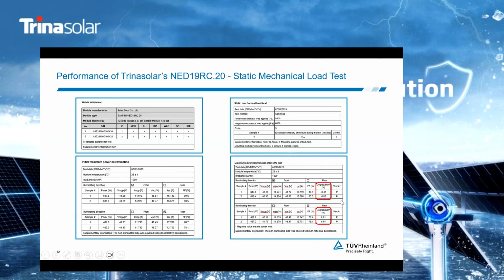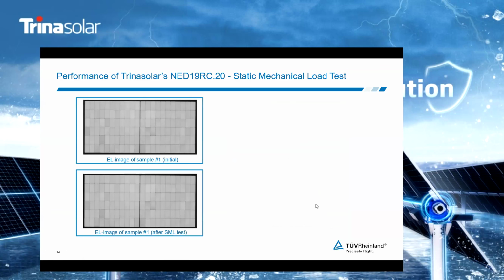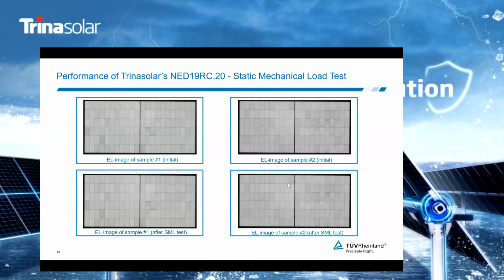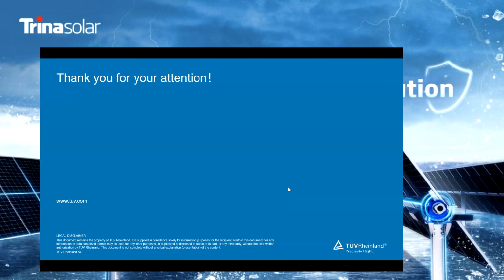For the front side, the power loss is still within 1%, which is already quite good. And for the rear side, we can see even a slight gain. Also, from the EL images, similar to its performance, the other sample's performance in the SML test showed almost no macro cracks. Okay, this is what I would like to share. This is all. Thank you very much for your attention.